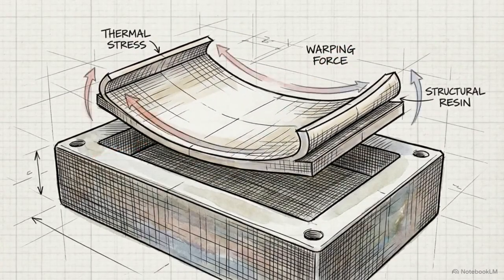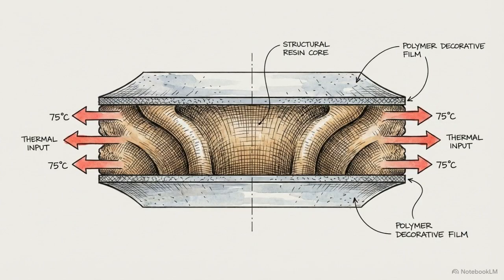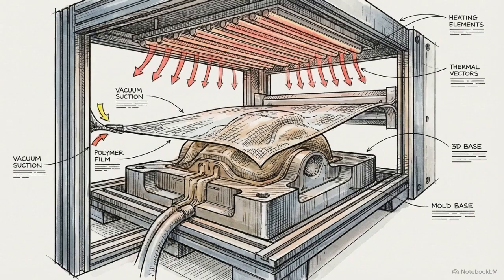A proven countermeasure is double-sided IMD. Applying films to both sides of the cavity simultaneously restores a uniform temperature field, keeping the core perfectly centered. For parts with extreme or steep geometries that make in-cavity placement impossible, manufacturers pivot to outmold decoration, or OMD. OMD relies on preforming the film externally under strict vacuum and heat, sidestepping the severe overstretching and non-uniform thinning seen on sharp corners in IMD.